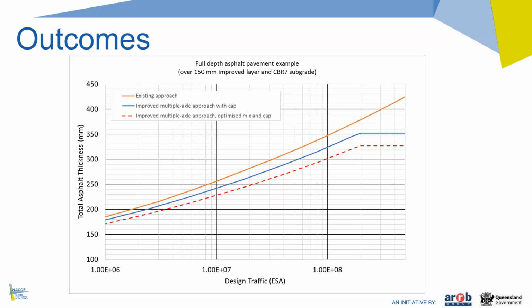So in this case, for this example, giving a thickness of 350 mm of asphalt. The limit would in fact be about 100 million ESAs if we continued to use the current traffic method where we convert traffic loadings into standard axles. So that's to give the same thickness of 350 mm for this example, which you can see from where the top line hits the thickness of 350 millimetres. So the upper limit on traffic, it's best to think of that as being 100 million ESAs, or 1 times 10 to the 8 ESAs using current traffic methods, but that's increased to 200 million, or 2 times 10 to the 8 ESAs using this new multiple axle method to give us the same thickness.